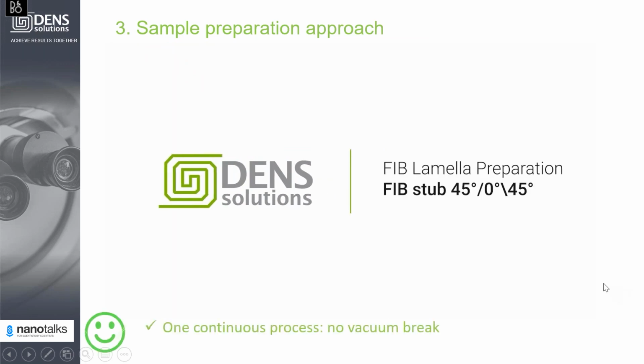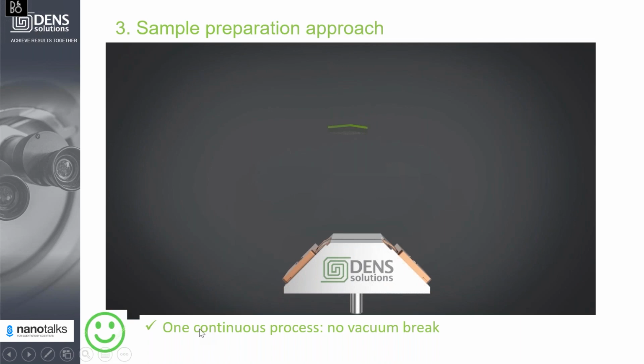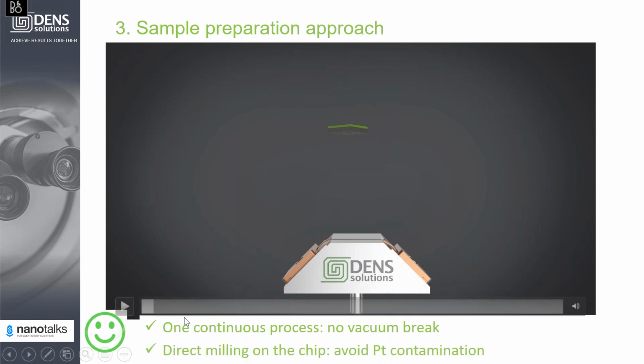So there are a few advantages of this process. First of all, in this process, the lamella preparation is done in one step. You don't need to break the vacuum. And another reason is we do the direct milling on the chip, which means we avoid any platinum contamination or any contamination that can come during welding or cutting or whatever.